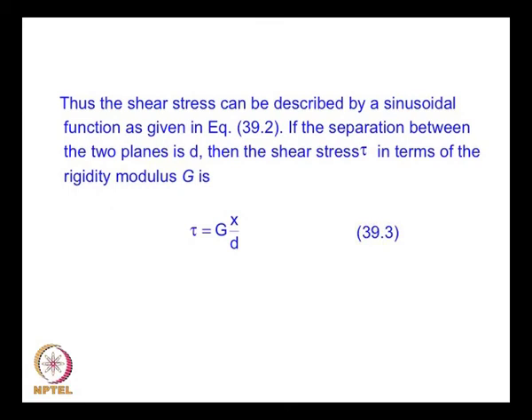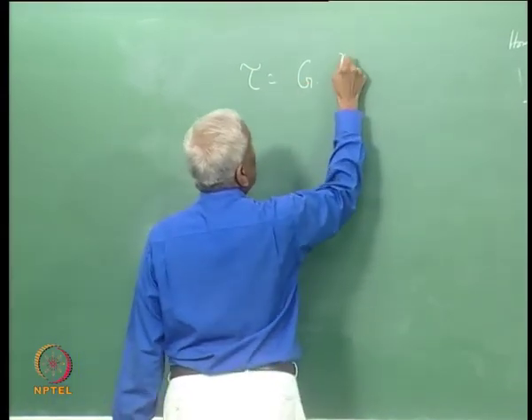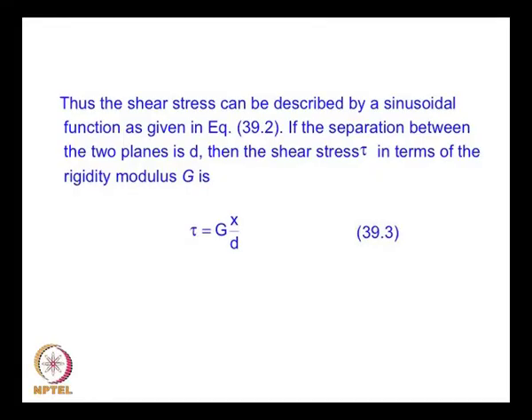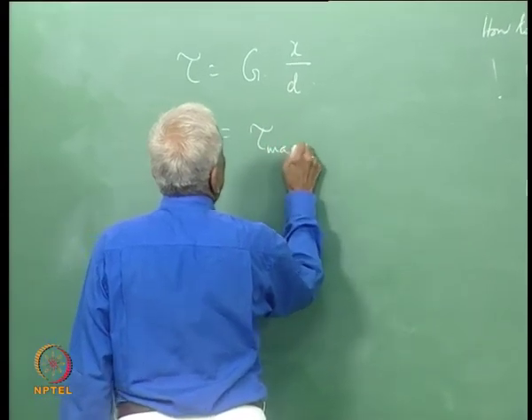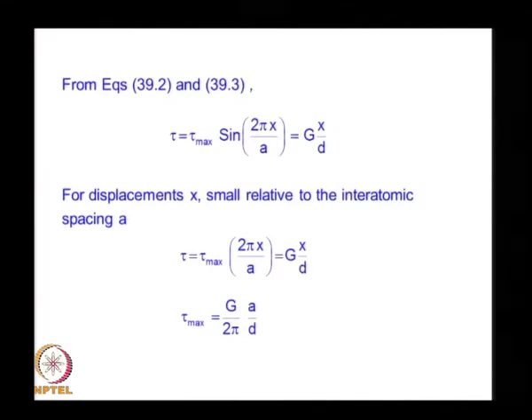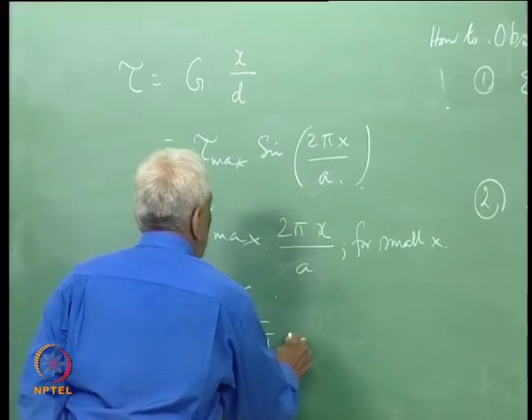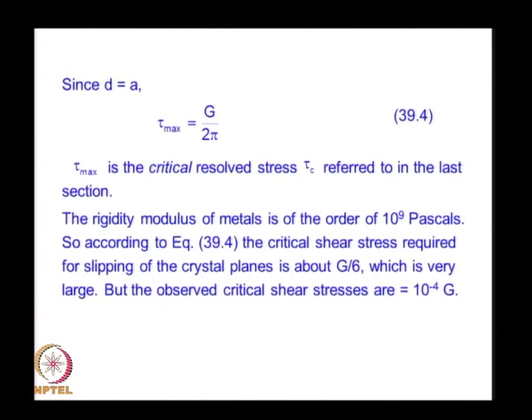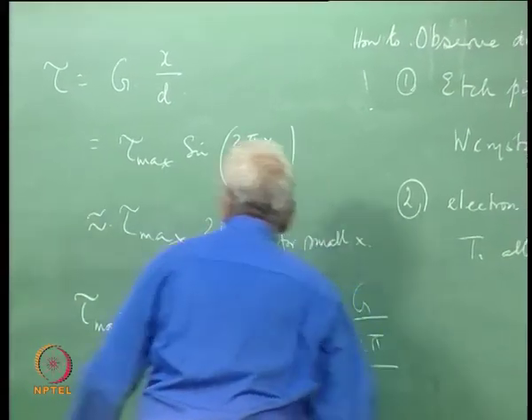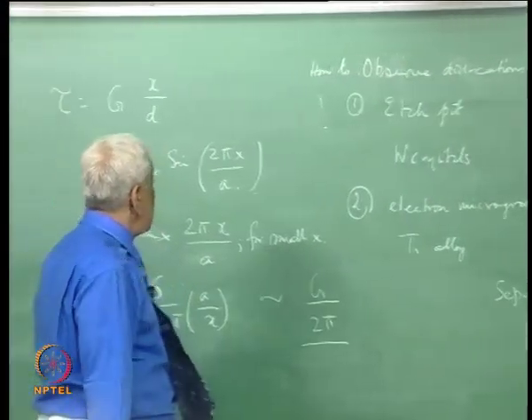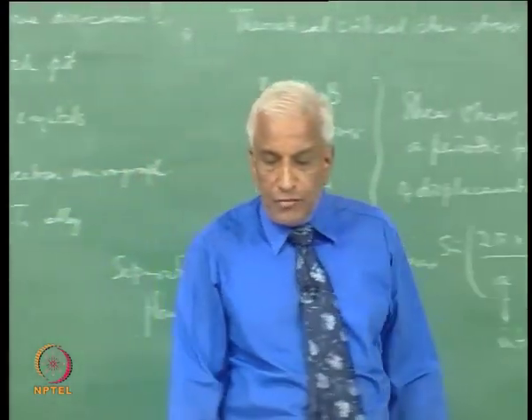So, the shear stress tau is G, the shear modulus, times the strain x by d. Therefore, this will be equal to tau max sin 2 pi x by a, and for small displacements we can replace the sin by its argument. Therefore, comparing these two we can write tau max as G by 2 pi into a by d. Since these are comparable, we have this as G by 2 pi. So, the theoretical critical shear stress is just about 1/6 of the shear modulus, which is a very large quantity,